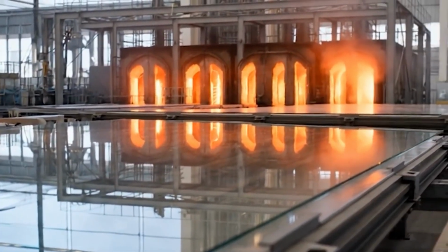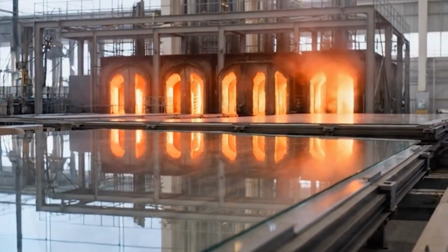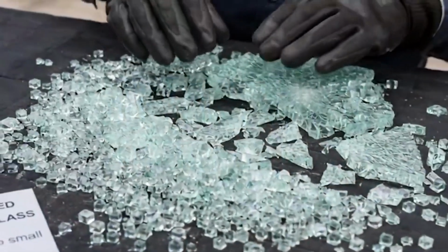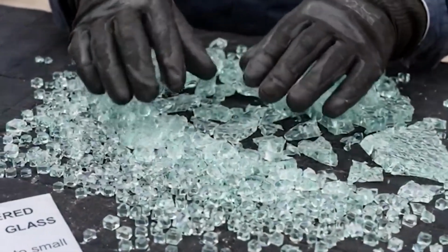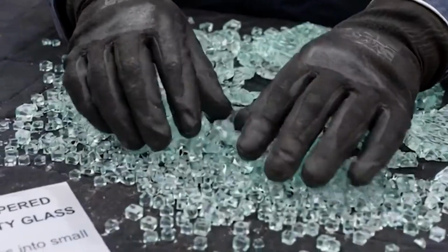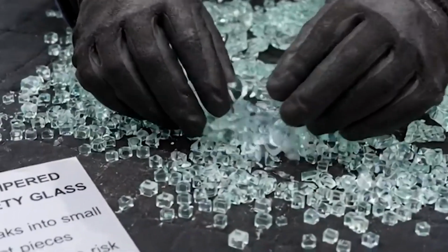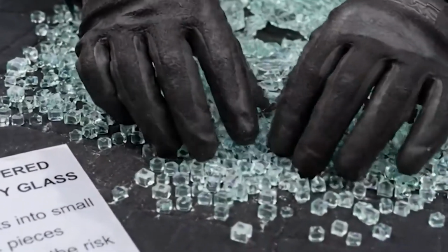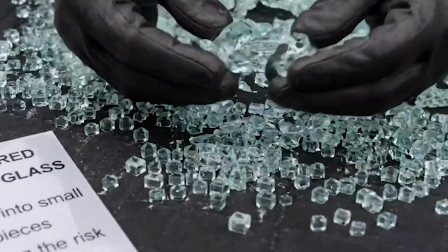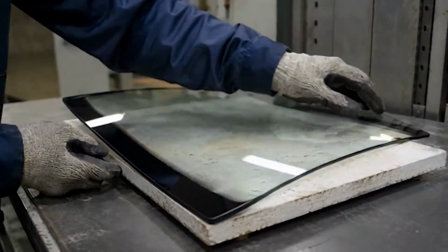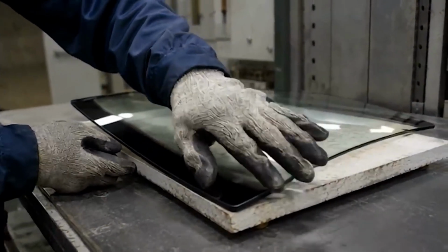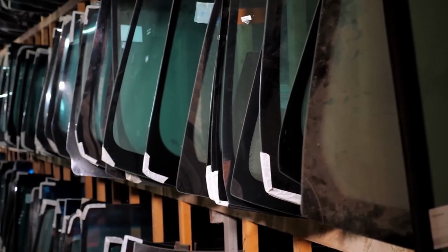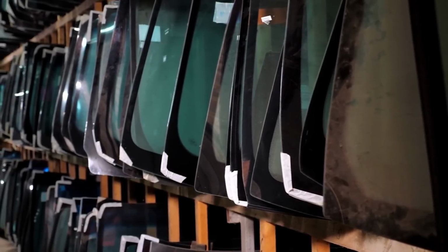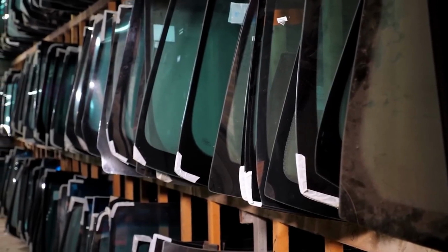But the black ceramic border absorbs heat much faster than clear glass. Inside the tempering furnace, the black sections became hotter than the surrounding transparent areas. When the glass cooled rapidly, large temperature differences created dangerous stress concentrations. Cracks began forming along the border. Manufacturers faced huge losses due to defective glass. The industry needed another solution. And that's when the famous black dots appeared.